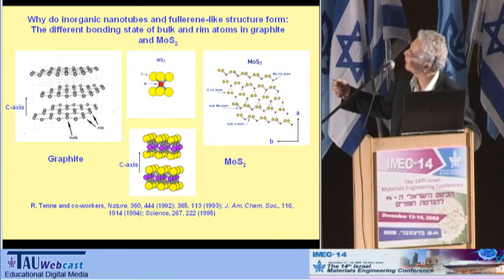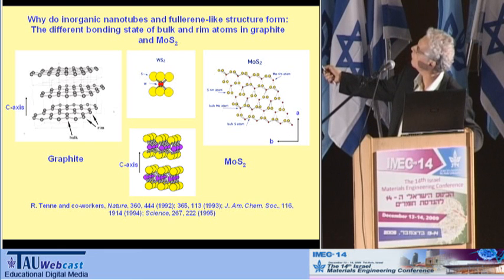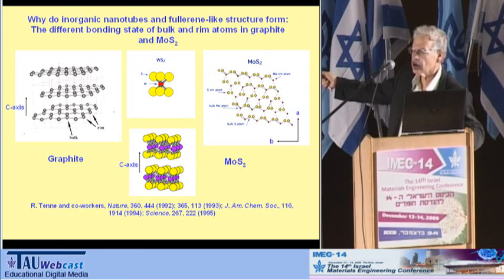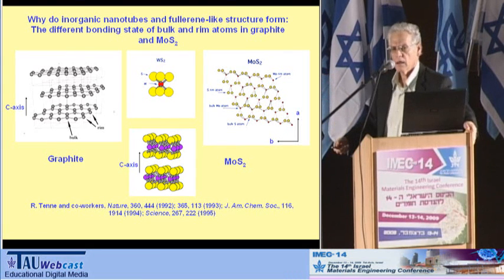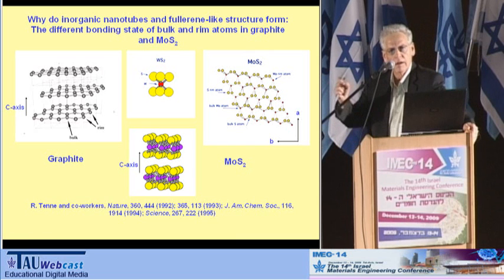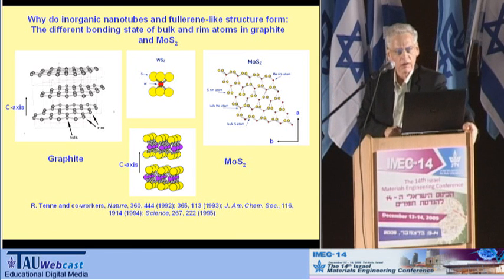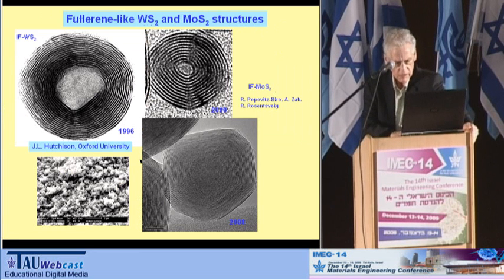Anyhow, the edge effects, which are prevalent in this kind of structure: there are always molybdenum atoms which are only 4-fold bonded instead of the bulk atoms which are 6-fold bonded, and therefore the structure becomes unstable in the nano regime. And once you understand it, you can try and synthesize nanotubes and fullerene-like structures from inorganic compounds with layered structure. And that's what we did.